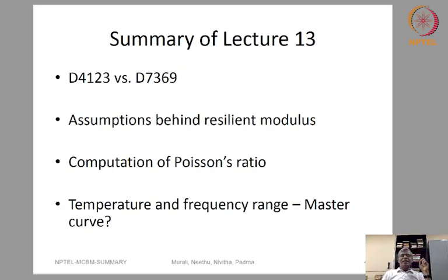One needs to very clearly understand the assumptions behind resilient modulus. The moment you talk about resilient, what you really mean is, after applying many cycles of loading, if you take the total strain, which consists of irrecoverable strain as well as the recoverable strain, the recoverable strain is called the resilient elastic strain, and they reach a steady state. So what you really want to do is to compute a modulus based on the resilient elastic strain. Now there is a problem here, because this particular test is conducted in the split tensile mode, what is really called the Brazilian test method.